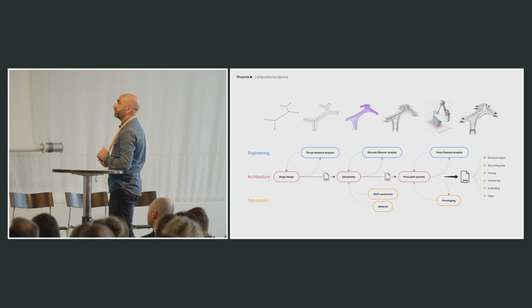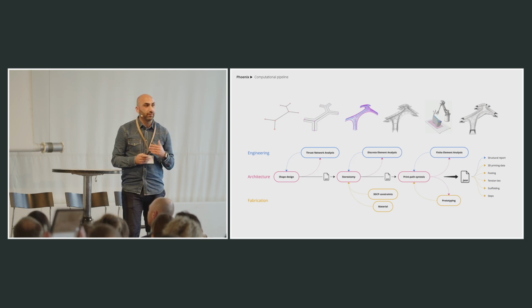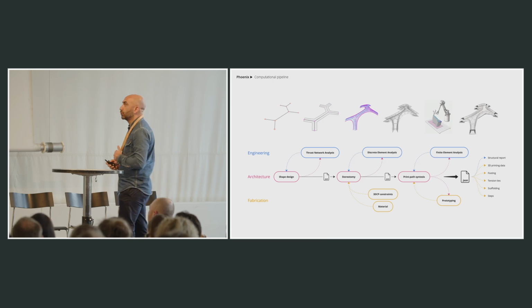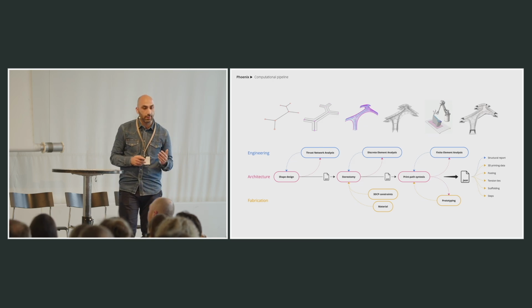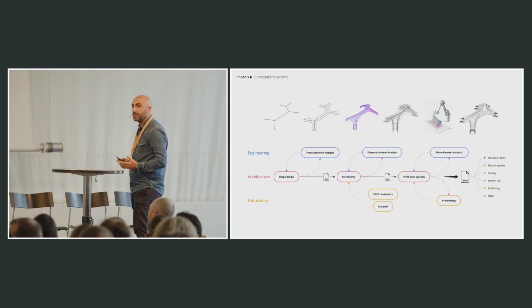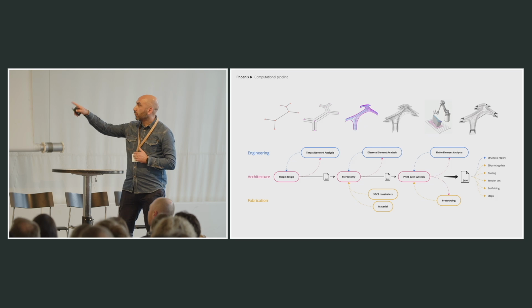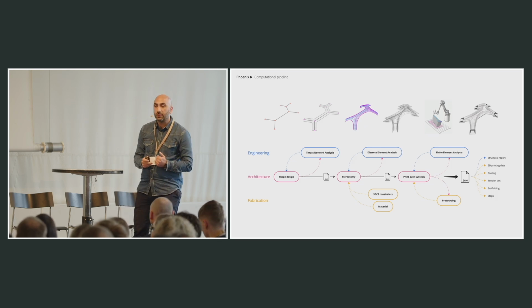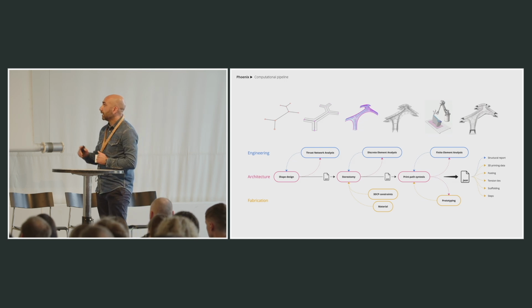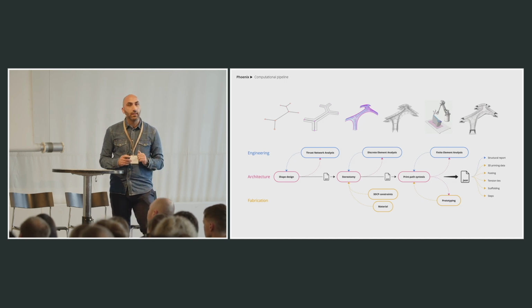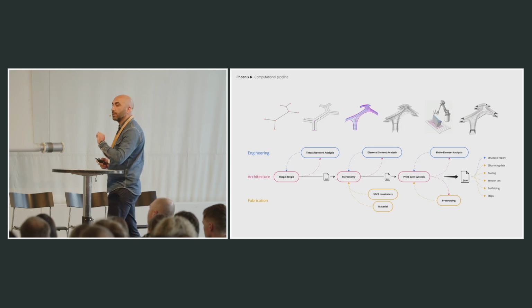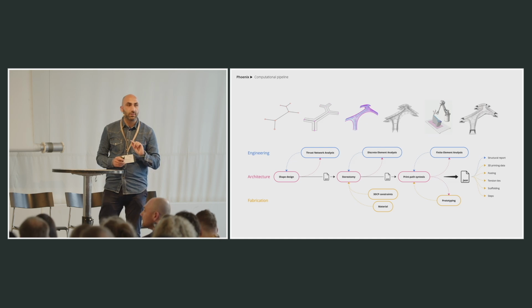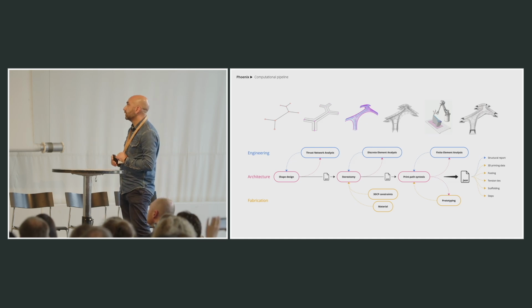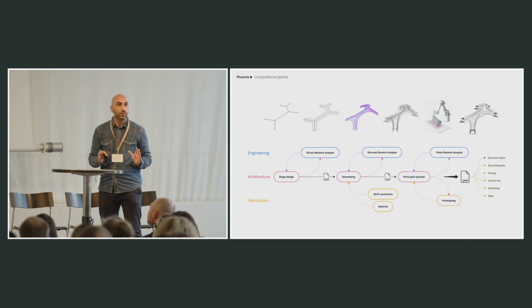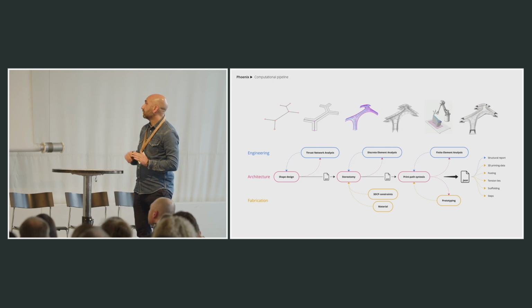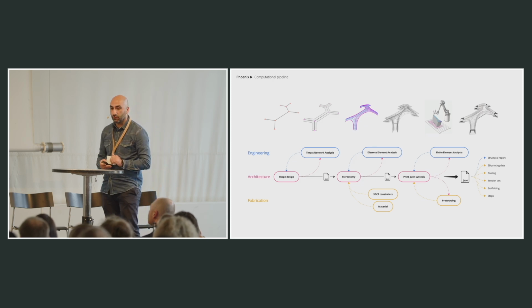So after the form finding through truss network, we gave this mesh thickness, we discretized the mesh, and we checked this through discrete element modeling analysis. So we understand the global equilibrium, the displacement capacity, and the load combinations. And at this point, we also introduced all the constraints coming from 3D concrete printing and from the material properties. And then finally, we checked locally with finite element analysis in order to define the thicknesses of the layers and, for example, the stiffening scheme inside the structure. And we populated this JSON file with all the data for fabrication, for structural reports, and for the robotic 3D printing of the structure.